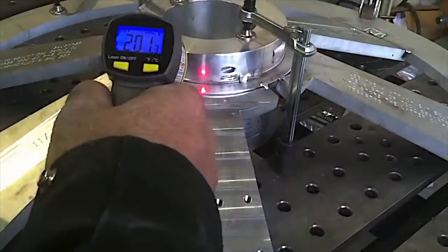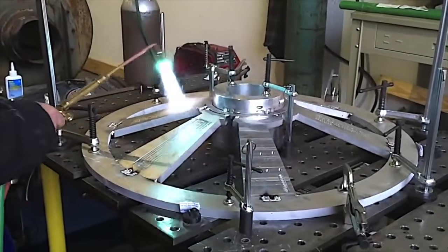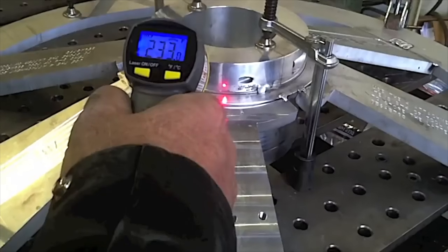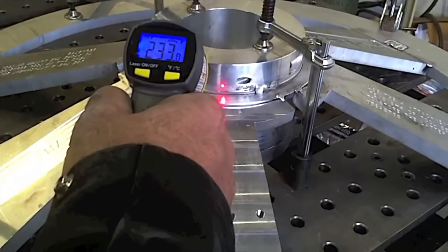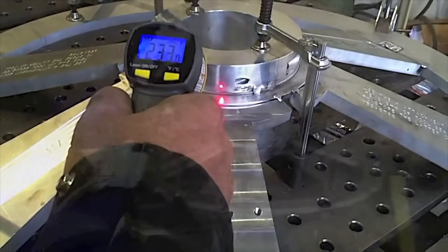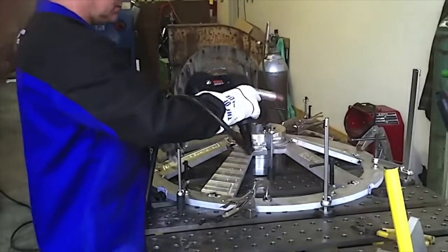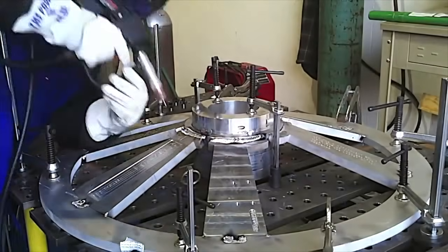Now, on a big thick chunk of aluminum like this, you preheat also a lot of times, but for a very different reason. Aluminum will not harden by getting hot and then cooling very quickly. In fact, it'll soften most of the time. But the reason we preheat aluminum is a very different reason. That's because it's so thermally conductive that it takes a lot of amperage to get a puddle going right away without a preheat. And also, preheat helps a lot of things like porosity on aluminum.